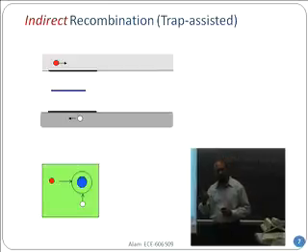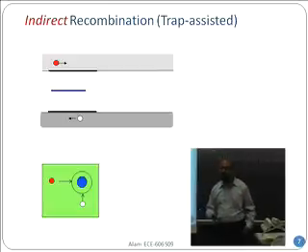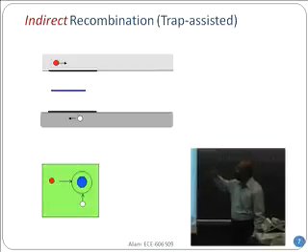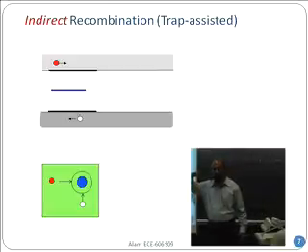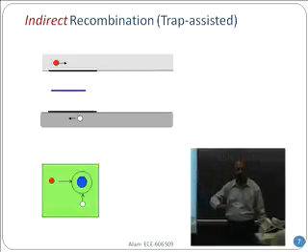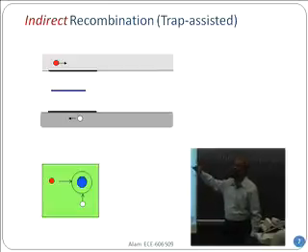Now, what is the distinction between a donor and an acceptor and a trap? Well, no distinction really. But I will show later the ones that are close to the mid gap. Only those can help in this process. If you are close to the conduction band like a donor, or if you are close to the valence band like an acceptor, then they will give away electrons, donors and acceptors, but they cannot help you in terms of recombination.